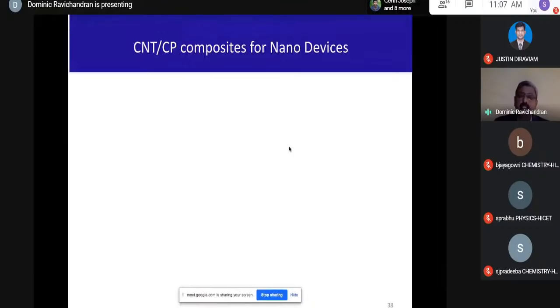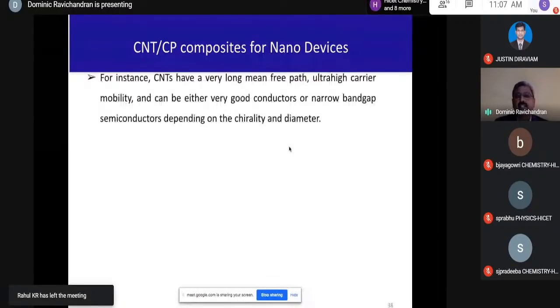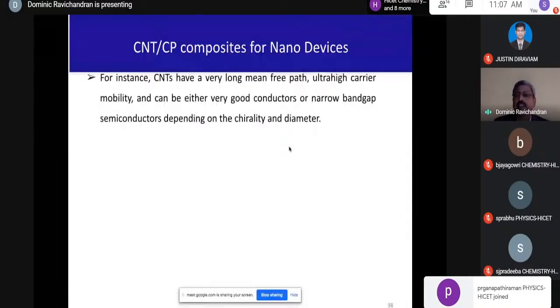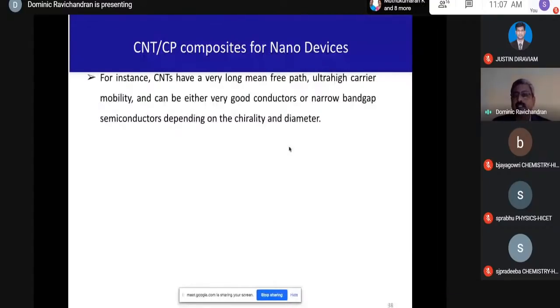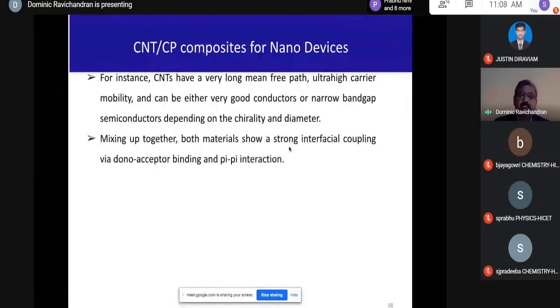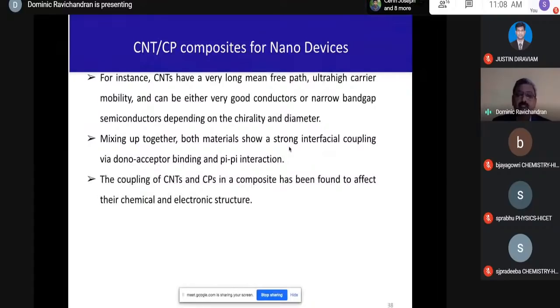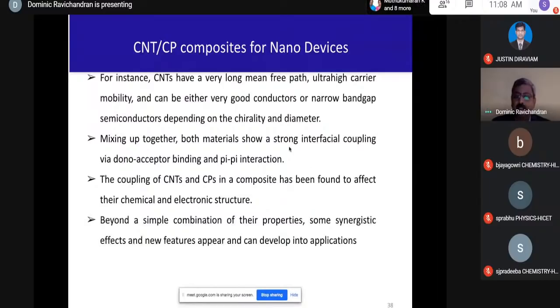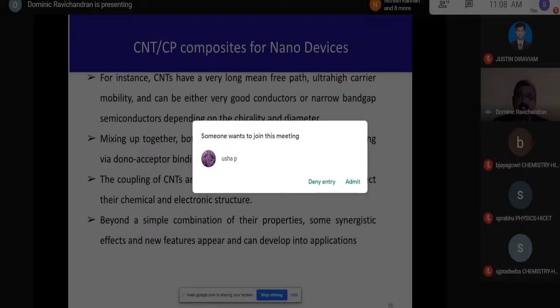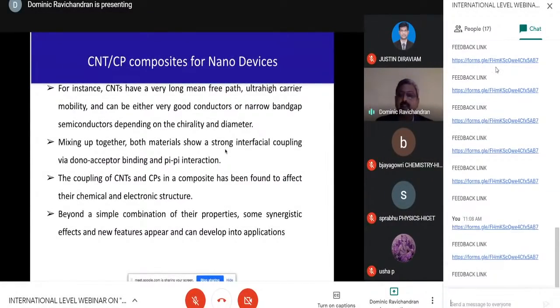In CNT-CP, that is conducting polymer composites for nano devices, the CNT have a very long mean free path, ultra high carrier mobility, and can be either a very good conductor or a narrow band gap semiconductor depending on the chirality and diameter. Mixing both materials, the carbon nanotubes and the conducting polymer, is going to give a composite with a strong interfacial coupling via donor-acceptor binding and pi-pi interactions. The coupling of the carbon nanotube and conducting polymer in a composite has been found to affect their chemical and electronic structure. Beyond a simple combination of their properties, it will be synergistic in effect, and new features appear and can develop into many applications.